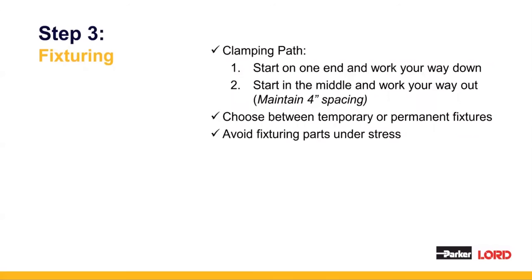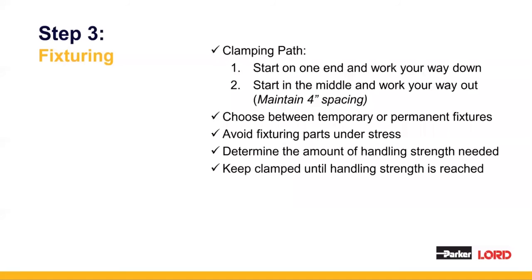For example, if parts are formed and they're pressing away from the substrate that you want to mate to, you're going to be building bonding stress into that, and it's going to want to already come apart. And then as the bonded assembly goes through the oven, the adhesive is going to soften slightly when it's introduced to that heat. That softening is going to lower the strength of the adhesive, and the part is likely going to come apart. So if you do have some formed parts, try and get them as flat and as smooth as possible before you're bonding them so that they don't come apart in the oven.